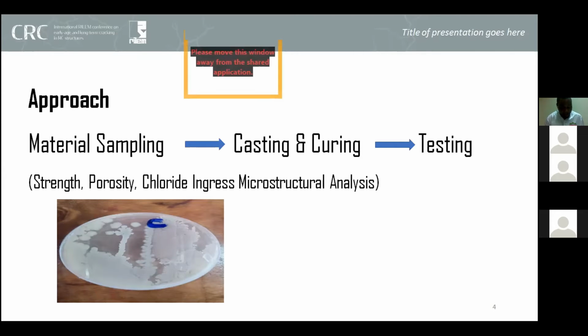In addition, half of the cracked and uncracked mortars were immersed in a bacterial solution containing Bacillus Subtilis, while the other half was separately immersed in curing water until the 90th day. Compressive strength, porosity, and chloride ingress were also repeated on the 90th day.